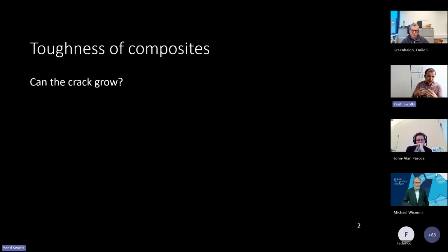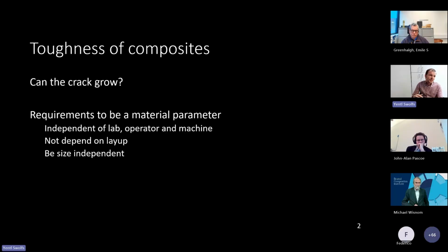In these workshops, we've often had a focus on trying to assess whether a certain property is a material parameter or not. If it is a material parameter, that means it's independent of the lab, the operator, the machine. It does not depend on the layup, and it should be size independent. And it's very much an open question whether this applies to toughness, because not depending on the layup is very doubtful for toughness. Not being size independent may also be doubtful, and it's very difficult to standardize some of these tests. So this is very much an open question in the specific case of toughness of composites, and maybe even more so in mode 3 and mixed mode.